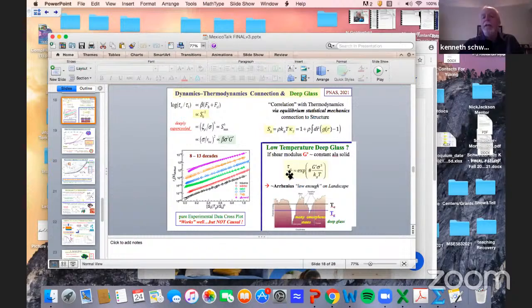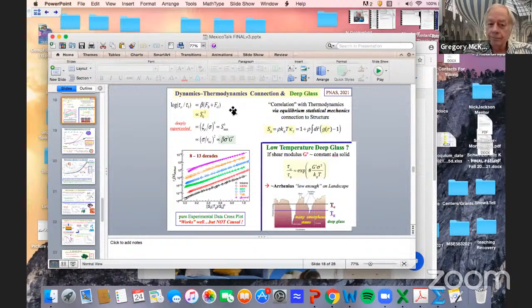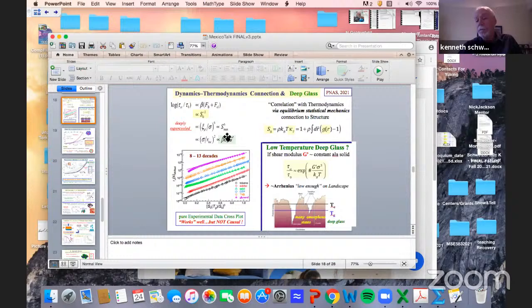That's why I said that we don't have a quantitative theory below TG, but certainly because we have these connections, if you just pick this one, since they're all equivalent in the range that they're applicable, then if the shear modulus sufficiently below TG, but equilibrated, approaches a constant, then we predict a crossover to Arrhenius behavior. So not only is there not a divergence, but there's a change from this supra-Arrhenius behavior. We don't have a quantitative theory for that because we don't have a quantitative theory of structure that low on the landscape. But just from the basic ideas of the theory, we have derived all of these. And I know of no other theory that's done something like that.